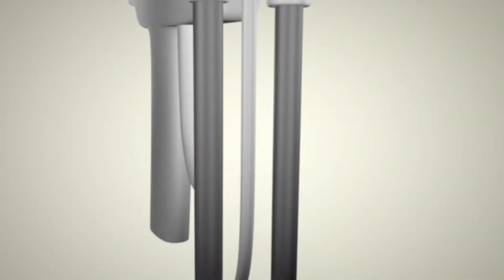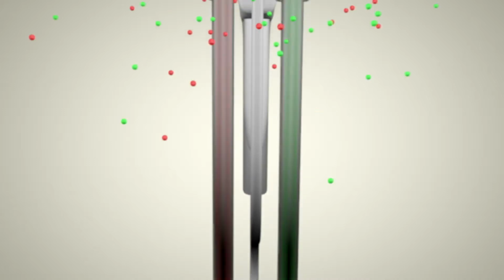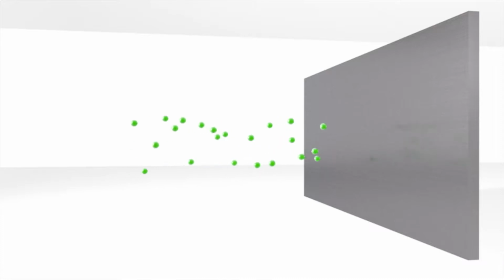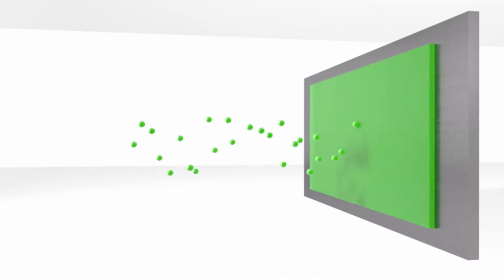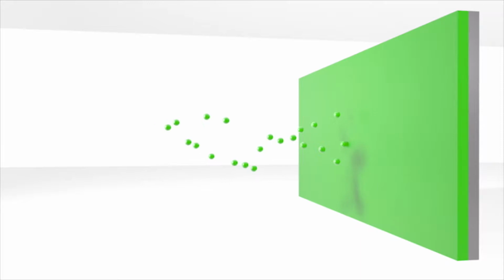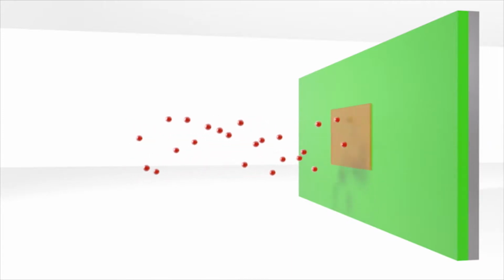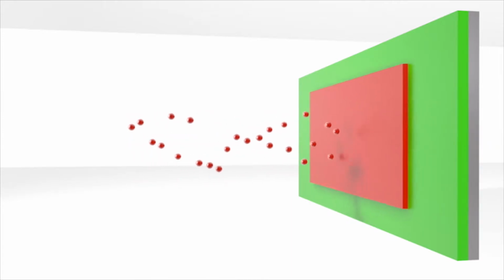Once EonCoat is sprayed onto metal, an alloy forms. The acid in EonCoat's formula reacts with the steel to form an iron phosphate layer. This iron phosphate layer is the first line of defense against corrosion. Then the chemically bonded phosphate ceramic functions as a second line of defense, a white ceramic top coat that continually leaches phosphate in order to prevent rust from forming. So the EonCoat you are spraying actually becomes part of the metal. It doesn't cover the metal, it becomes part of it as a true alloy.